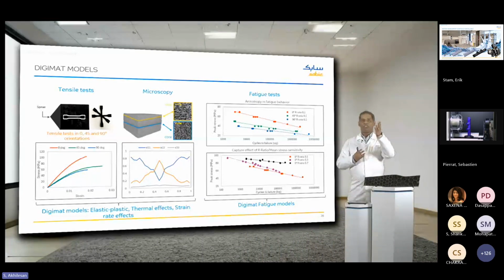Now, once we perform the tensile tests as explained by Vamshi and the microscopy information as explained by Sebastian, we can combine these two data in Digimat MX to obtain elastic plastic material cards. You can add additional effects such as temperature and strain rate by performing additional tests on the tensile test. So you basically get elastic plastic or thermoelastoplastic material cards or viscoelastic viscoplastic cards, depending on the type of test that you perform.